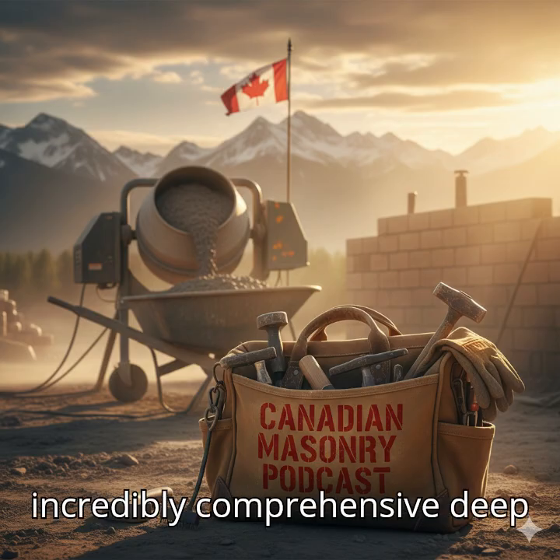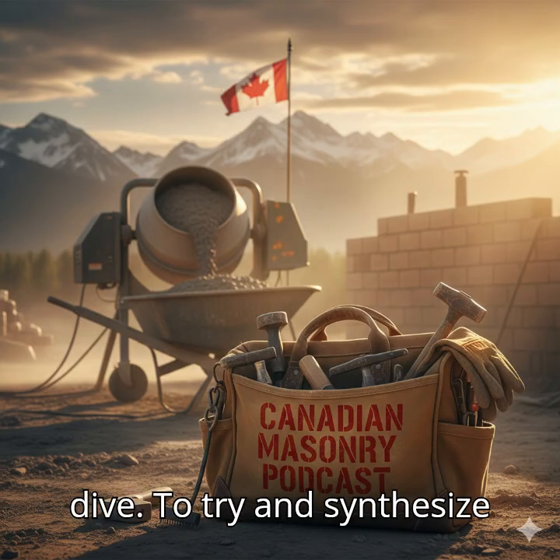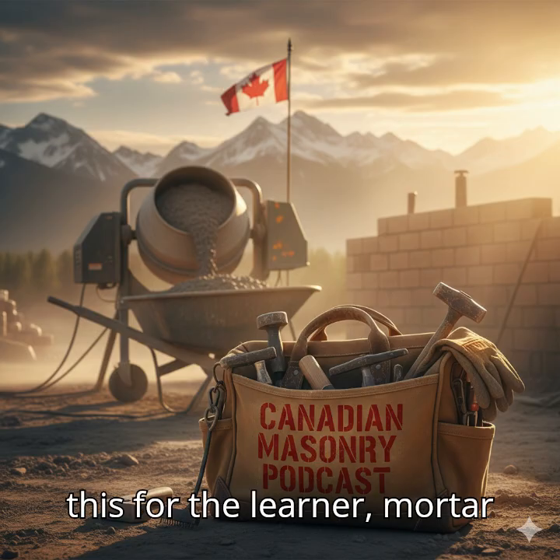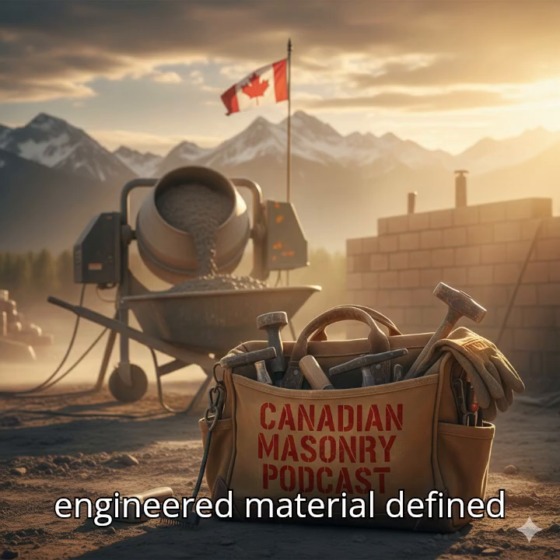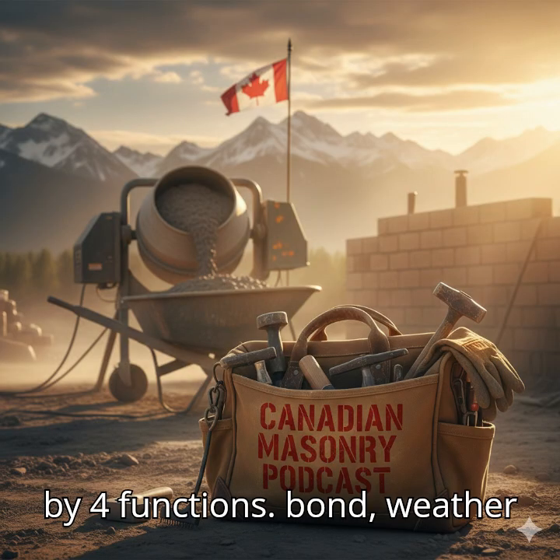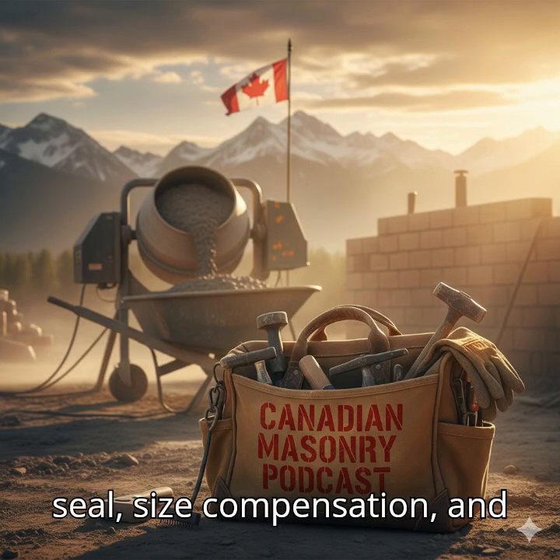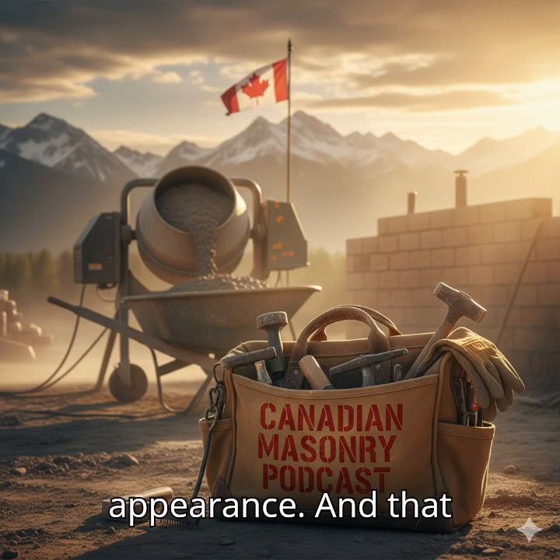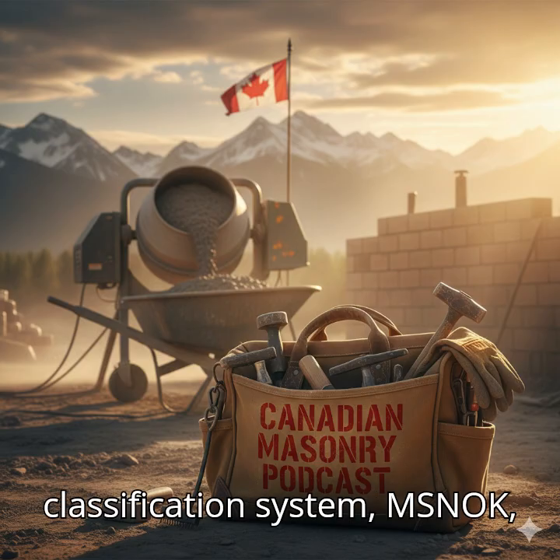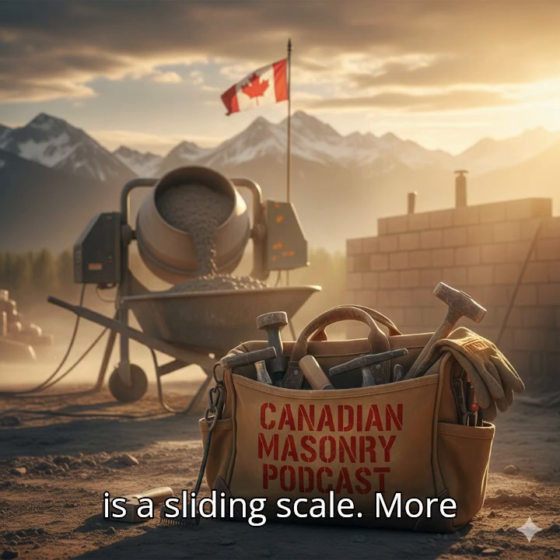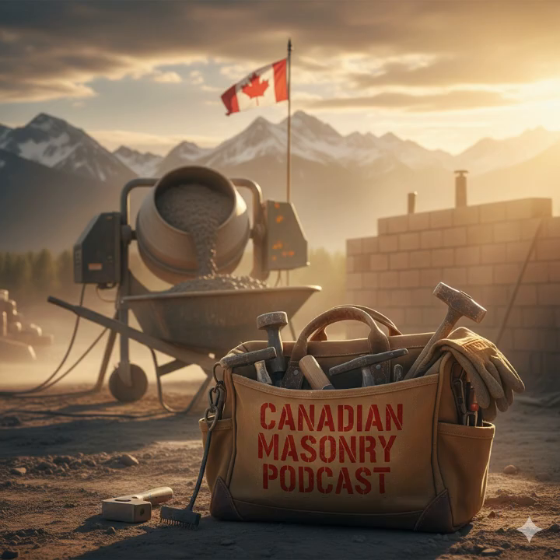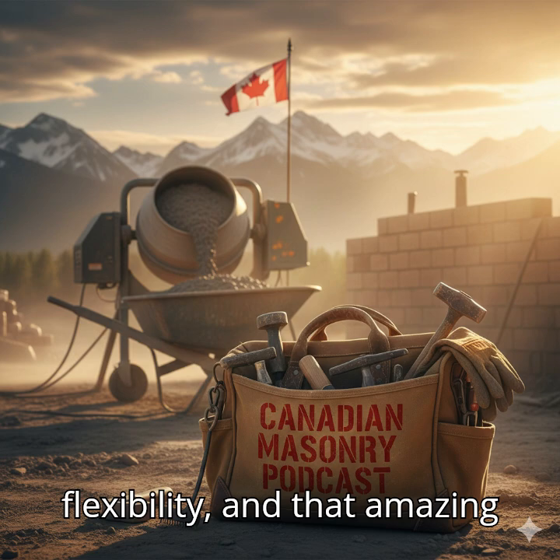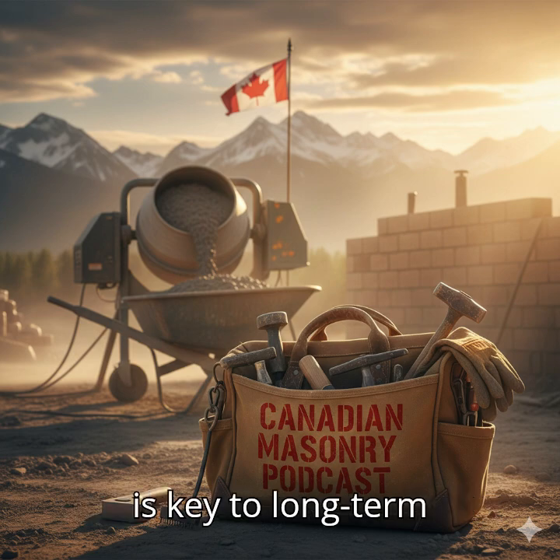Exactly. We have had an incredibly comprehensive deep dive. To try and synthesize this for the learner, mortar is not simple. It's an engineered material defined by 4 functions: bond, weather seal, size compensation, and appearance. And that classification system, M-S-N-O-K, is a sliding scale. More cement means more strength, but also more brittleness. More lime means more flexibility and that amazing self-healing ability, which is key to long-term durability.